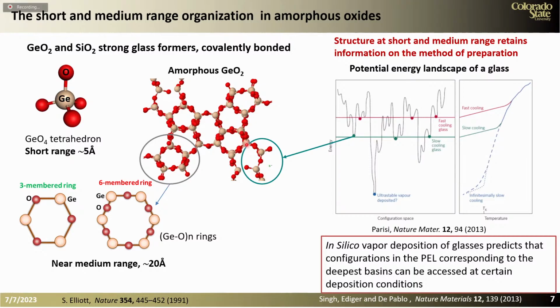Now, recently, there have been model simulations that predict that glasses that can achieve a state defined as an ultra-stable state can be obtained by growing these coatings by sputtering. And what is this ultra-stable state? Well, this ultra-stable state is essentially a configuration in which these rings at medium range show ordering. And this ordering is represented in the potential energy landscape as a very deep well.